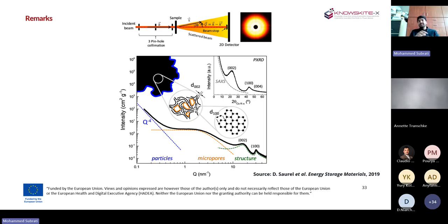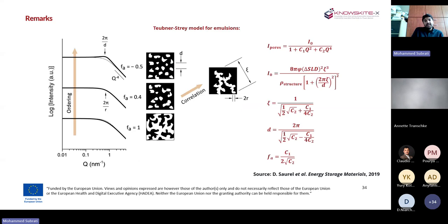And you can see that the pores are created simply by the bending of the constituent graphene stacked layers, which, if you remember the previous slides, is why in the powder XRD patterns the 002 reflection was very broad. The reason for the broadening is that they tend to create the pores. They are the structural material for the pore walls. SAXS can give you very insightful information into the pore structure, especially for the pore ordering, and also to quantify it.